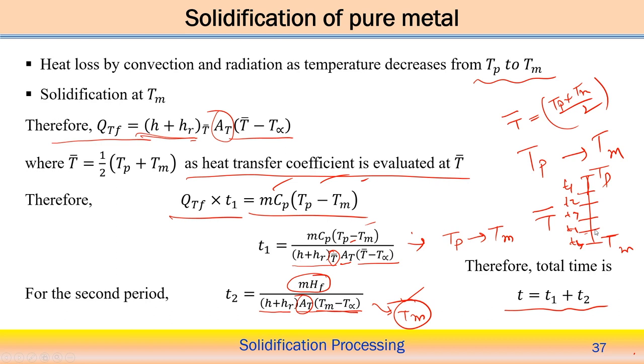So in that case, total solidification time can be the summation of T1, T2, T3 plus T4 plus T5, like that. In this way, if we calculate so many steps in between, then the accuracy of calculating the values of the heat transfer coefficient will be more. That is why in this case we are considering two different time steps: one from the peak temperature to the melting point temperature, and then the phase change at the melting point temperature. So we count only two time steps, T1 and T2, such that the total solidification time T equals T1 plus T2.